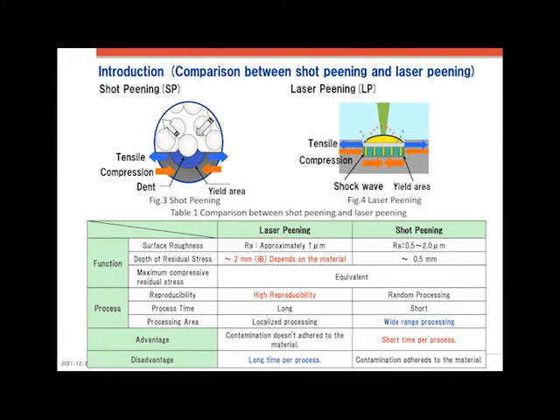On the other hand, laser peening is a technology to peen the surface of the workpiece by irradiating a pulse laser in water, or where water flows over the workpiece. I'm sure you all know what I'm talking about, so sorry, I'll skip the detailed description. Laser peening can introduce deeper compressive residual stress, higher repeatability, and more localized processing compared to shot peening. However, when processing a large area, laser peening takes more time compared to shot peening.